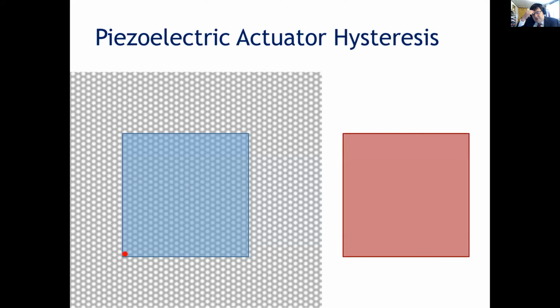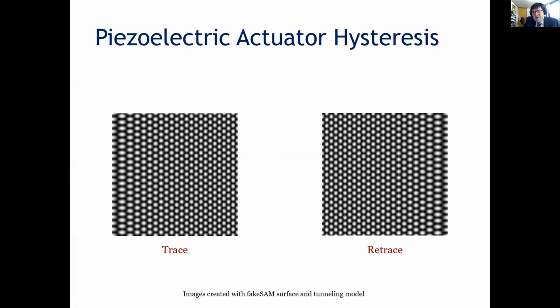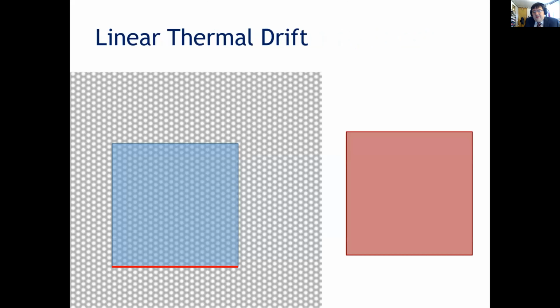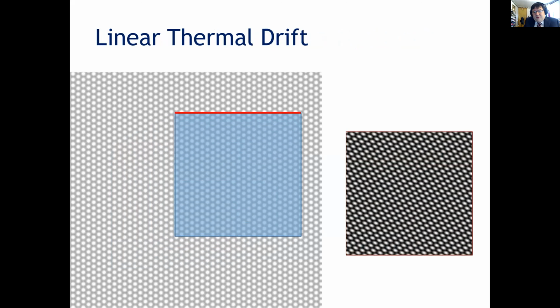So here's what it might do to an STM image. If you think of the left side as what the STM scan probe is doing, and the right side as what you see on your computer screen. So the controller is scanning the tip at what it thinks is constant velocity, but it's actually not constant. And so that causes one side to be stretched out and the other side to be squished. And exactly the opposite happens on the retrace. At the beginning, it's stretched out, and at the end, it's squished. And so you get images that are exaggerated here, but this is what might happen if you had hysteresis in your images. You can also have linear thermal drift. So I have a window that the STM scan controller is planning to trace, but if that window moves over the surface while I'm scanning it, then I get a distorted image.